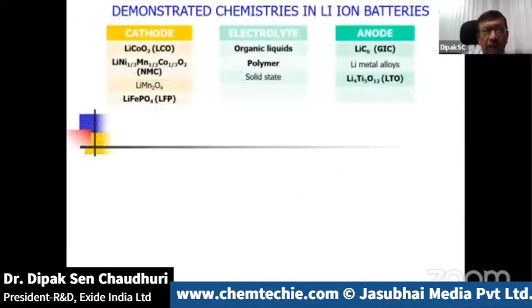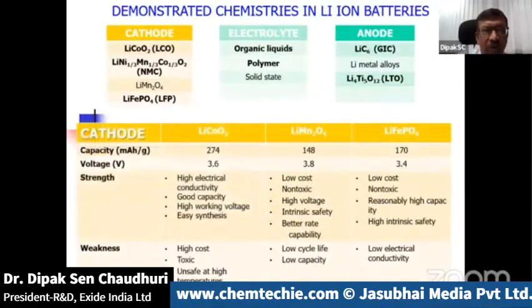So typically, some of the very common versions that we all know are the NMC, where we talk of the cathode material, a lithium compound, which also has nickel, manganese, and cobalt. It can be lithium iron phosphate. Now, if you're talking of nickel, manganese, cobalt, you can get very high energy density, but also very high cycle life, even up to 4,000 or 5,000 cycles, but may not get the safety and the other features that you get in a lithium iron phosphate, which has a lower energy density, somewhere in the range of 120 to 140 watt hours per kg, but will give a much more stable performance. And typically, it's a more preferred version for energy storage application from the safety point of view.